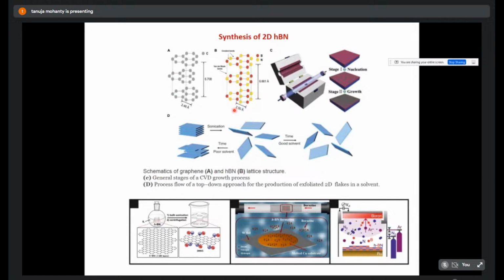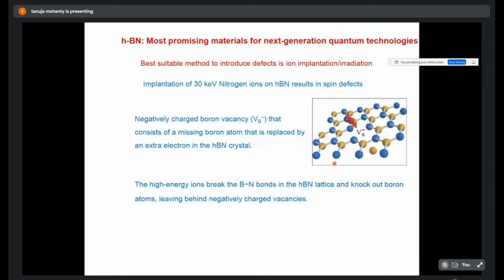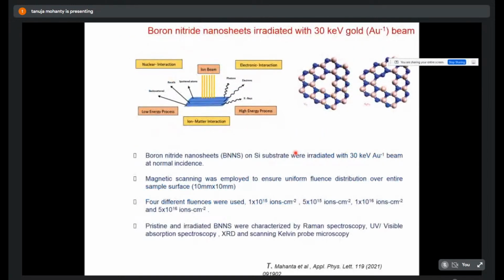So then I'll tell about what we have got in 2D hBN. The hBN, as I said, can be synthesized either by CVD or by the chemical method. Here they are prepared by the chemical method. Now we have not used the swift heavy ion beam; rather we have used a very low energy ion beam, 30 keV nitrogen ions. As we have seen previously, we expect vacancies to be created: the boron vacancy and the nitrogen vacancy. We'll see which vacancy is easier to produce, and which will outweigh the other. That is this type of defects.